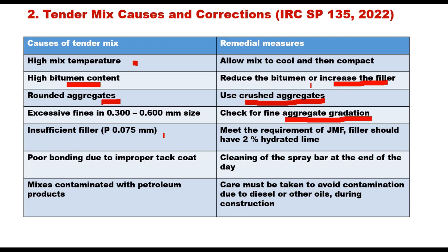Insufficient filler should meet the requirement of the job mix formula. Filler should have 2% hydrated lime. Tenderness can also be caused by poor bonding due to improper tack coat, and this problem can be removed by cleaning the spray bar at the end of the day. Mixes contaminated with petroleum products such as diesel or other oils can also be tender, so care must be taken to avoid such contamination during construction.